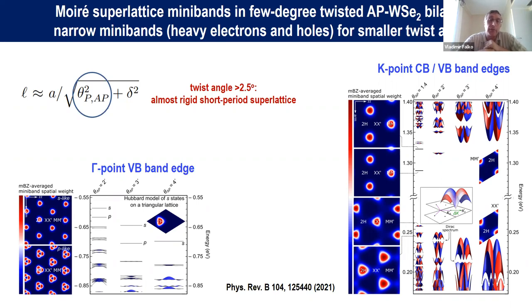So one has to worry about what happens with the minibands around the gamma point band edge in those materials. And also there is interesting physics that may happen at the Q point due to the interlayer hybridization as well. So what is shown here on these plots is how the minibands change when the angle decreases, and what you see is that they systematically get narrower. And this is not a very difficult thing to expect, because when you have band edges and when they're modulated for heavy carriers, you get objects which start resembling more and more quantum dots.